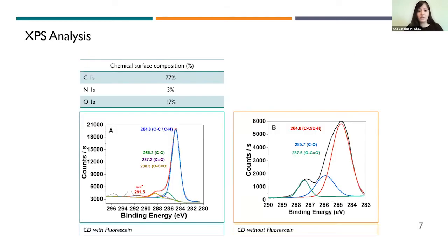The surface composition of these carbon dots was characterized by XPS analysis, where the carbon dot with fluorescein showed a chemical surface composition of 77% carbon, 3% nitrogen, and 17% oxygen, and by comparing both spectra, the presence of a pi-to-pi contribution in the carbon dot with fluorescein spectra, which is absent in the carbon dots without it, indicates the presence of fluorescein-like structures in the surface of the nanoparticle.